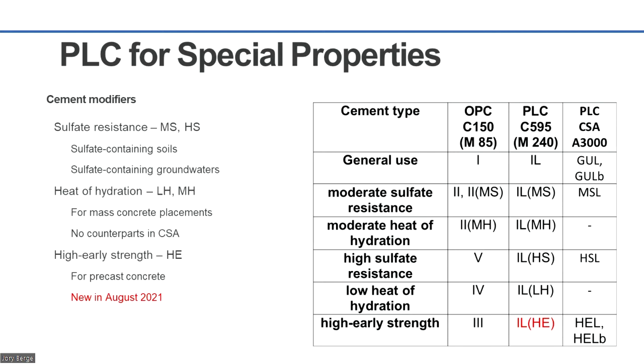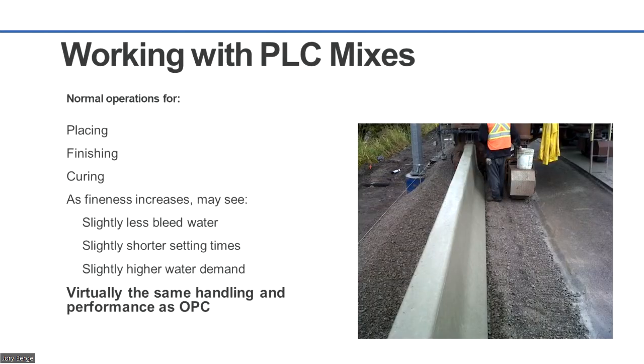And if you have not gotten familiar with them, just know that you can get them in any flavor you want. So if needed in a 595 blend, they can be high early, they can be moderate heat, they can be high sulfate. It depends on what your market demand is as to what cements would be available for you. And when it comes to mixtures, especially for paving, the things to look at would be what type of bleed rate and set times that you might get. And again, the perception is often that it's going to be a delayed set. And what you might get is a quicker set based on a 1-to-1, but it again depends on the blend.